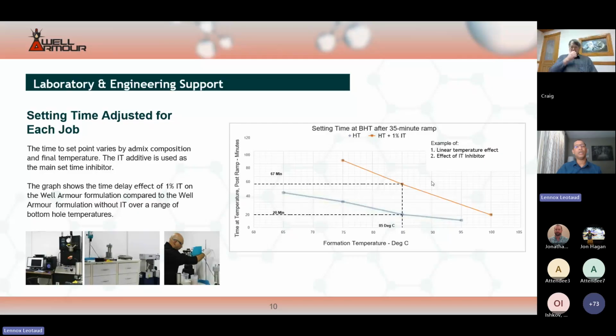So the Well Armour slurry set times, with or without the addition of inhibitor, are pretty predictable and also repeatable. And the set time test that's performed in the lab is also pretty transferable to what you would see in the field when you use the system. So if you do a test and you get, say, 90 minutes in the lab for your set time test, under the same conditions in the field, that's what you're going to achieve in terms of a set time with the Well Armour system.